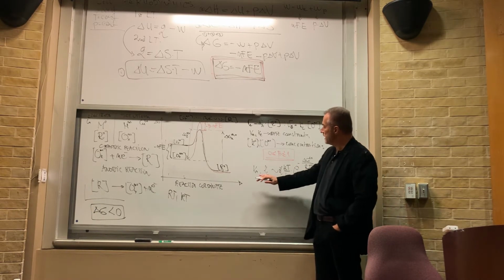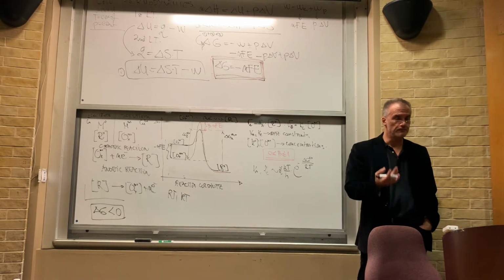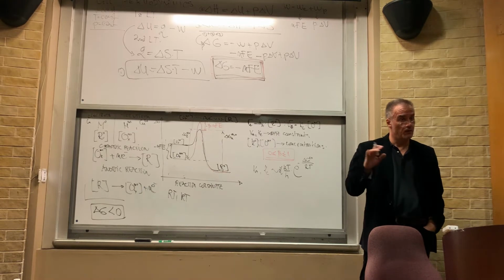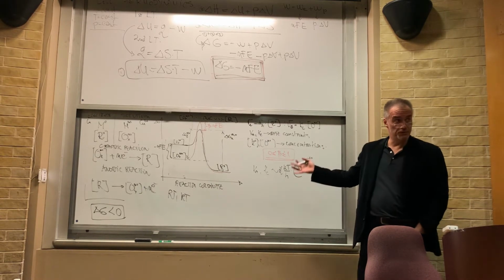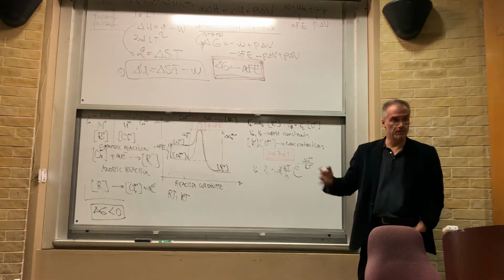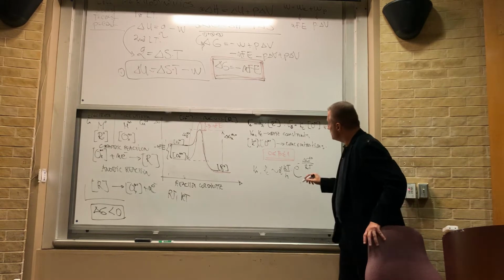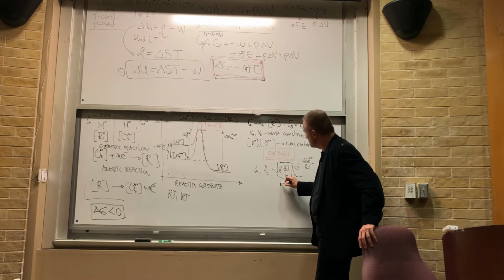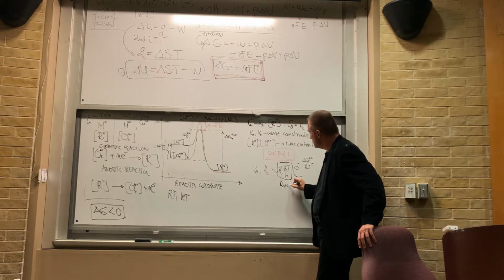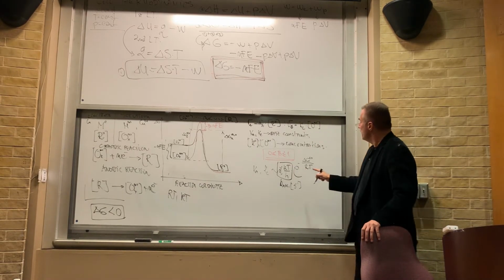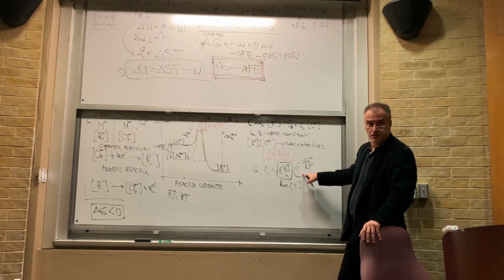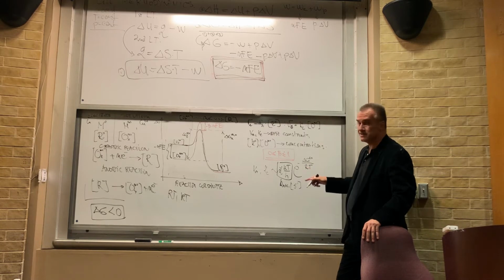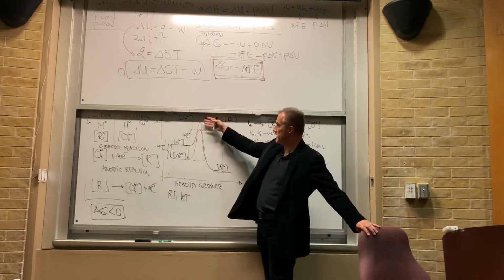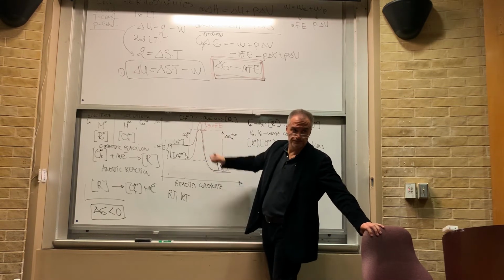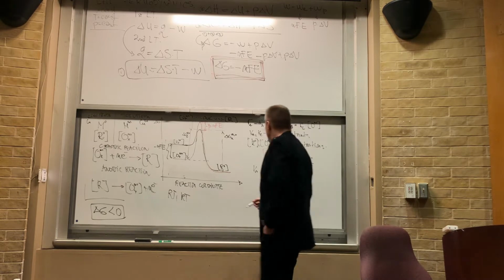So what we really have is that this rate constant has the form, which is something that you heard in Arrhenius theory, and this is a little bit modernized Arrhenius theory from the point of view that we know a little bit more about statistical mechanics and typical terms and so on. But the bottom line is this: that this term here, and I'm going to call it K naught, whether it's A or C, doesn't matter. It has the units of frequency, and you can check yourself. And this term here is an exponential term that is basically similar to what you know from Arrhenius theory, where this delta G is like activation energy, but it's actually the free energy of the activated complex, right? Okay. So we can define now Ka